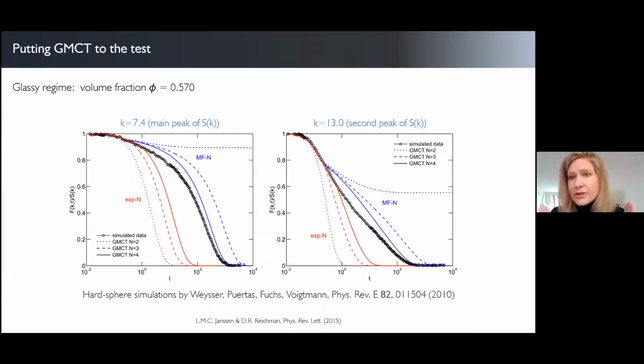And that's a two-particle correlation function. But it's plausible that as you get closer to the glass transition, you also have to start worrying about 3-particle or 4-particle or n-particle structural static correlations that also contain important information about the structure. And so it's plausible that as we get closer to the glass transition, the theory also needs to know about those higher order structural correlations to get a really accurate prediction of the dynamics. And so that's something we're also working on right now, to incorporate those higher order structural correlations as additional input to the theory to then predict the full dynamics.